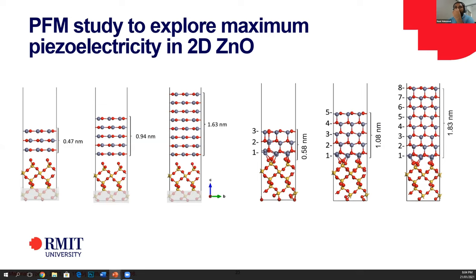Then why are we getting this performance? We studied it further, because we are developing this on silicon dioxide, and silicon dioxide is giving some distortion in the structure. Then we investigated further, did experiments again and again, and found that a covalent connection between the silicon dioxide and the zinc oxide is the main triggering point. That is creating a buckling in the structure, and ultimately we are getting such a high performance when we reduce